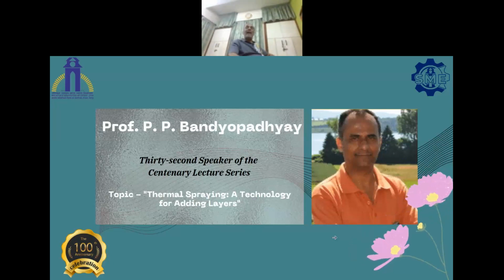The objective is to melt the powder so that it heats and sticks. You have to make sure particles do not cool off, particles do not bounce off after cooling, and the substrate is not overheated. These things you have to keep in mind and set your distance. The range for plasma is typically 100 millimeter. For HVOF, we can go up to 300, 330 millimeter. That's the range roughly.